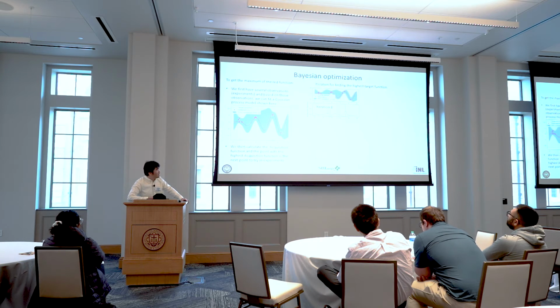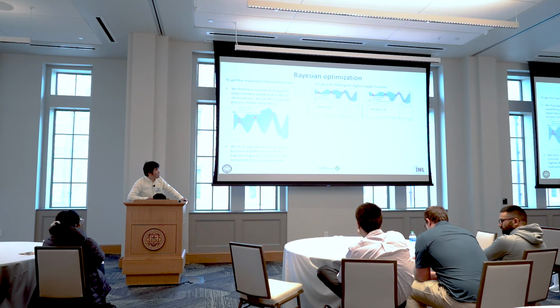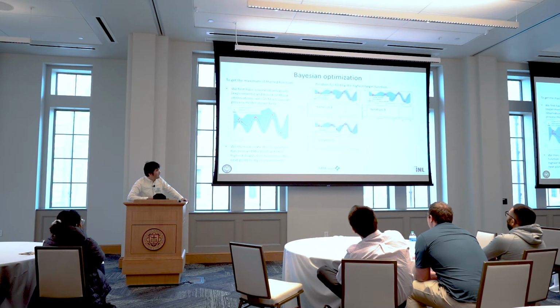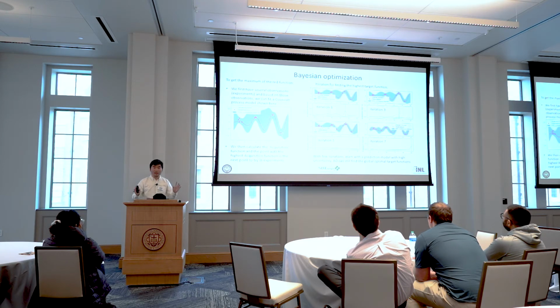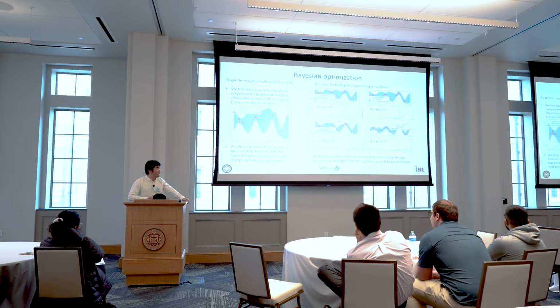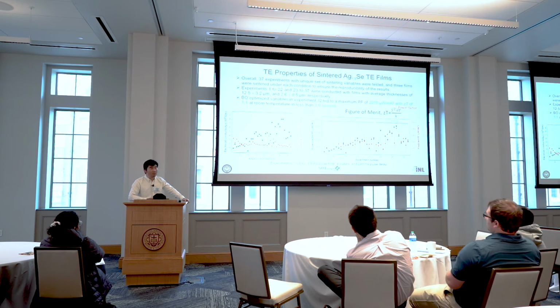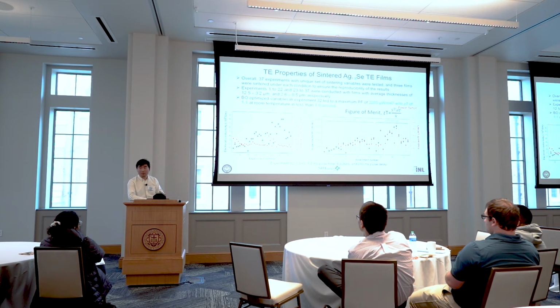So in iteration 1, this is where the Bayesian optimization tells us to collect a point. Iteration 2, still around this area. Iteration 3, then iteration 5, it asks us to collect the data here. And iteration 7, it has us collect the data here, and that turns out to be the maximum. All right, so this is a 1D problem. We can visualize it in this parameter space. But our optimization of the sintering is a 4-dimensional, actually later on 5-dimensional problem. We cannot visualize that, but the idea is the same. We use Bayesian optimization to tell us where to collect more data until we find the maximum.